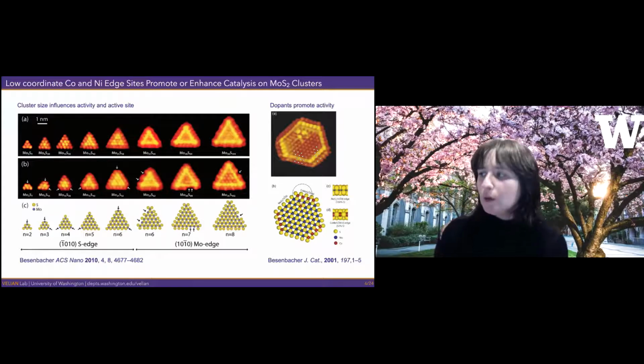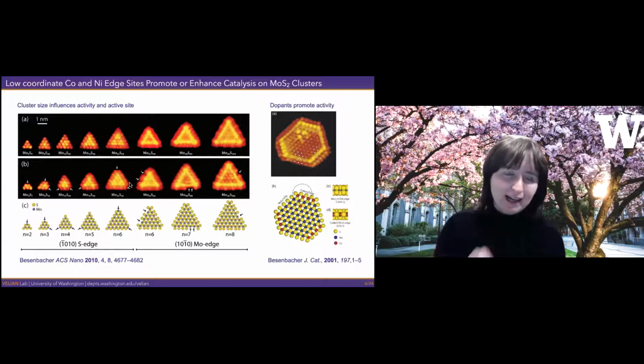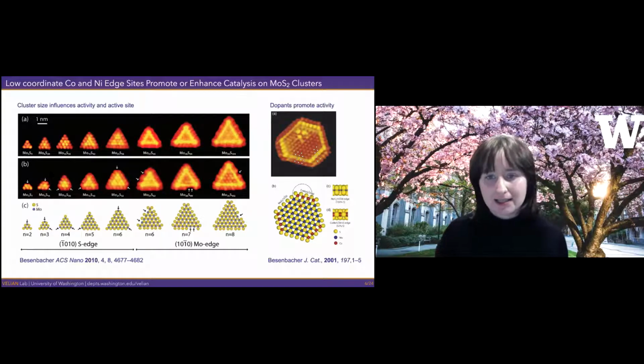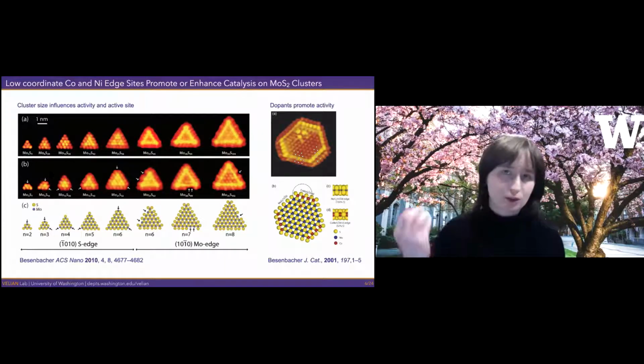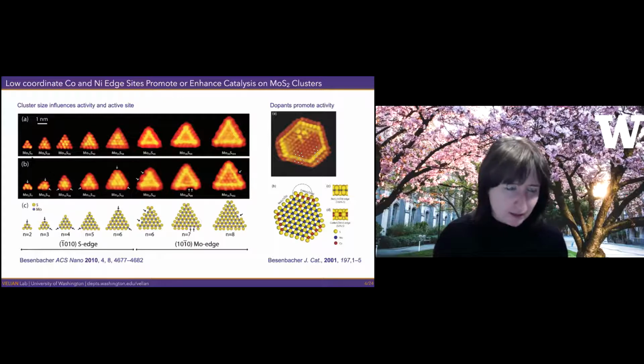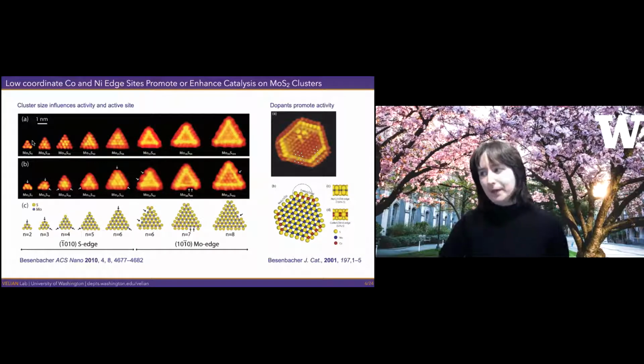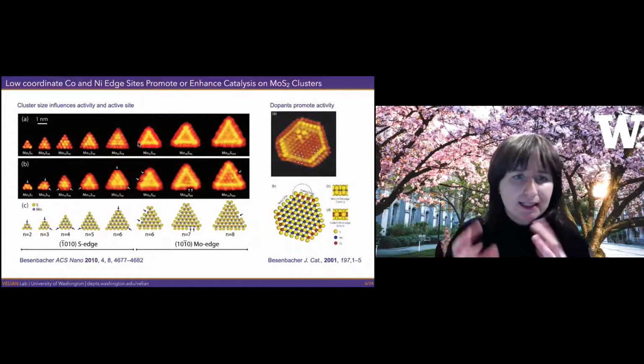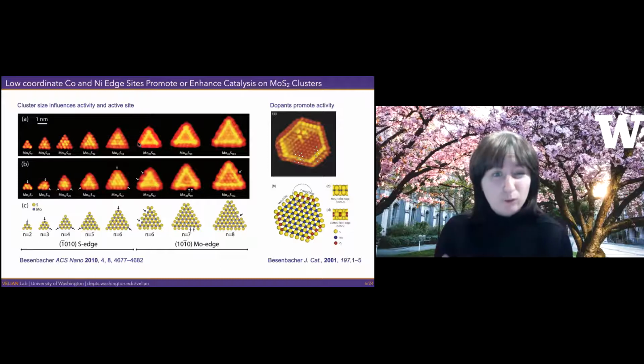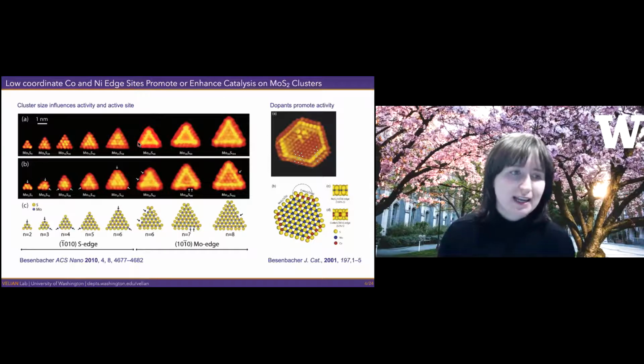And so I guess the images that are shown here, these are STM. So you really image a single flake and then see what happens in operating conditions. Where are these active sites that exist, as you perform the reaction? For example, you abstract a sulfur from a petroleum product, and this desulfurization is an important transformation. And it really enables us to get an atomic level understanding of what happens at the active sites and how this transformation is done, which in turn might help us think about how to make better catalysts for all sorts of other transformations.